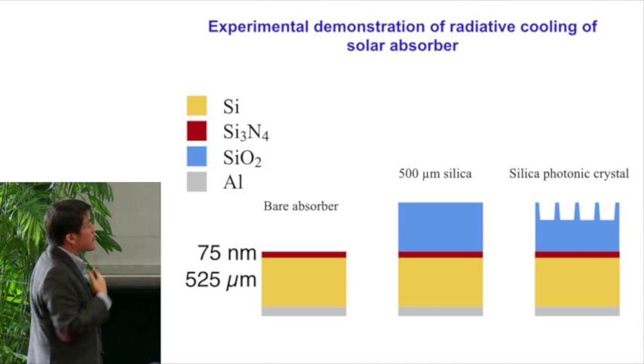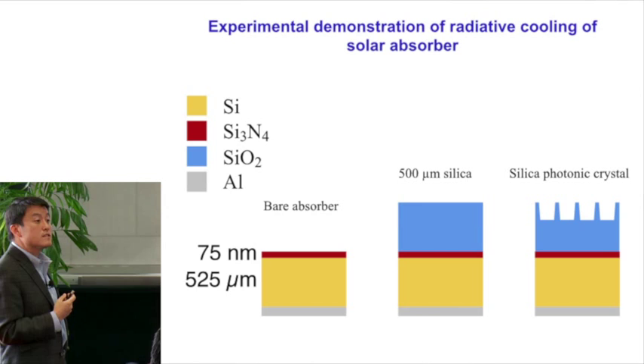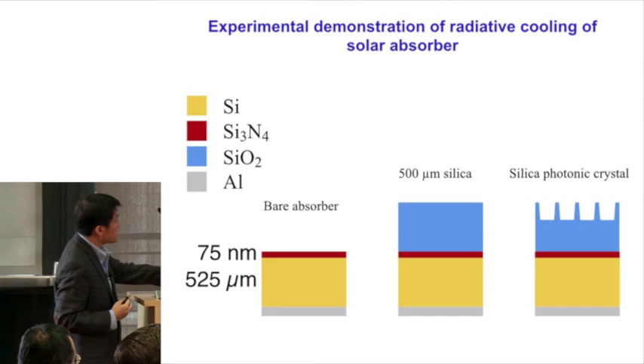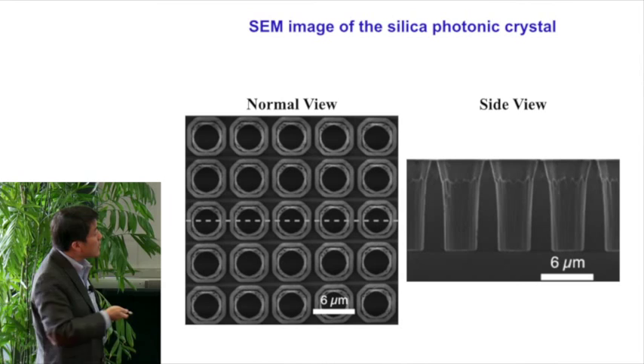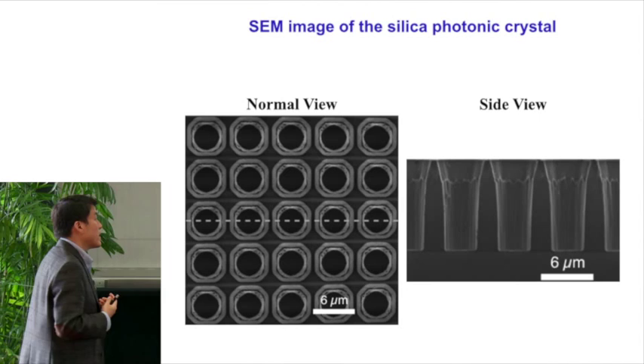And then we also compare that with a structure with a silica photonic crystal on top. And that was optimized for thermal radiation properties. So this is the SEM image of a silica photonic crystal. The periodicity here is on the order of 6 micron or so, so that you get enhanced thermal radiation. And we compare these three structures.